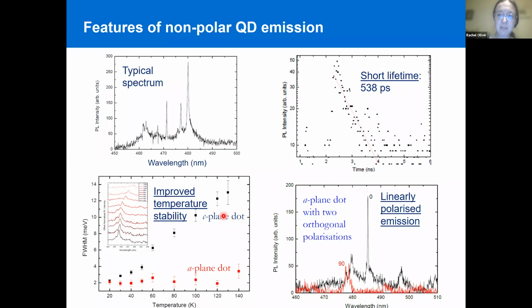But we also discovered that there are other things that are quite interesting and quite nice about these A-plane quantum dots. They are more stable to temperature than the C-plane quantum dots. Here I'm looking at how the line width of the quantum dot broadens against temperature. And the A-plane dots remain very narrow, even up to about 140 to 150 Kelvin, when the C-plane dots are significantly broadened. Also, the light from these A-plane quantum dots tends to be linearly polarized.